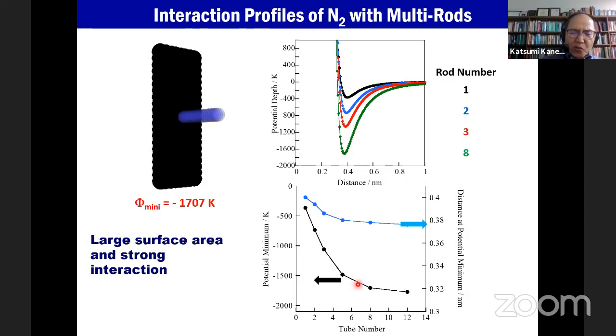So if we want to get strong interaction, we need some wall with a little bit of width. So a single rod is not necessarily good. So we must compromise. So probably 5 rods or 8 rods, a little bit narrow and wide, this wall system should be very good for the high surface area and also for very strong interaction potential.